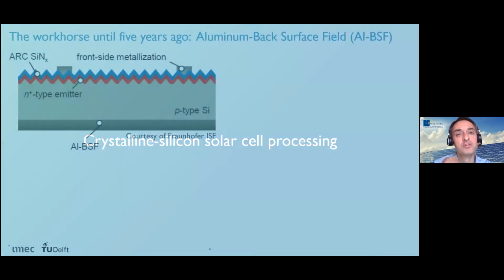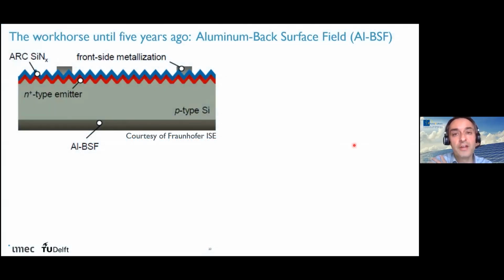Here I'll give you a bit of the history of how this went. Until 5 years ago, the main cell concept used in silicon photovoltaics was the so-called aluminium back surface field cell, shown here. It's a relatively simple cell structure where you use a P-type silicon wafer, mono or multi, and make at the front an N-type emitter. You texture the front surface so that you have better light incoupling.